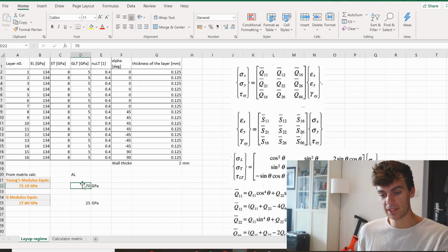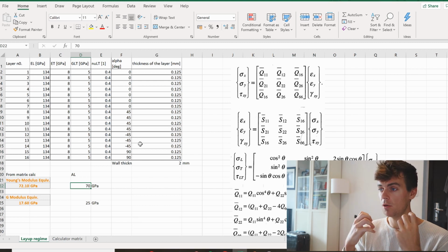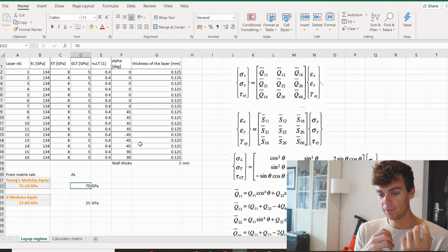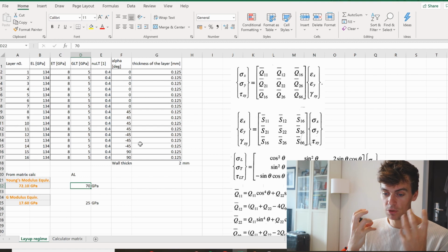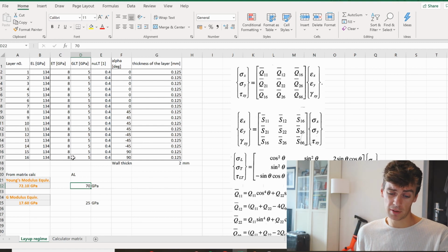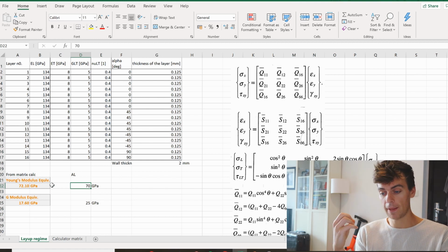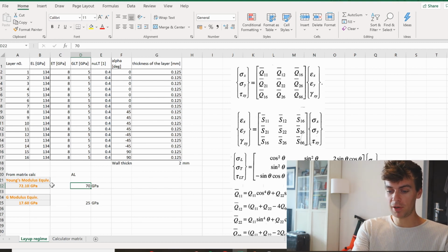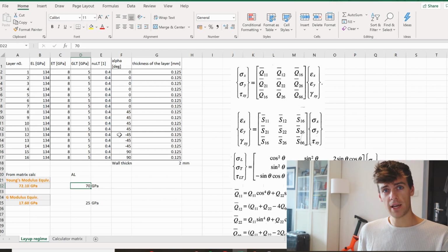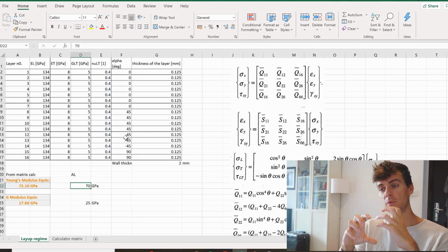Now, this layup for the down tube was just kind of a guess: I've got half the fibres going 0, half of them going 45 for torque. It's just half and half bending and torque. You can increase the bending stiffness up to around 100 gigapascals, so you've got about 50% stiffer than aluminium. But if you replace some of these 45 degree layers with more 0 degree layers, you're going to lose the torsional rigidity of the tube, which is also important.